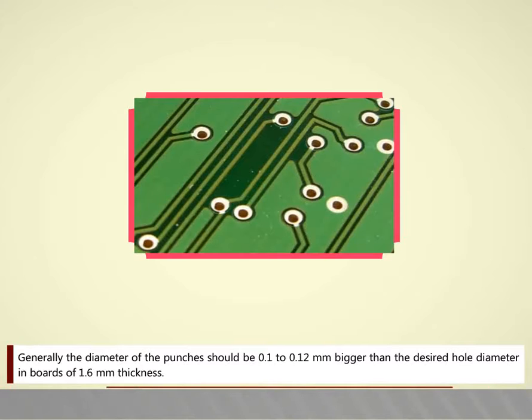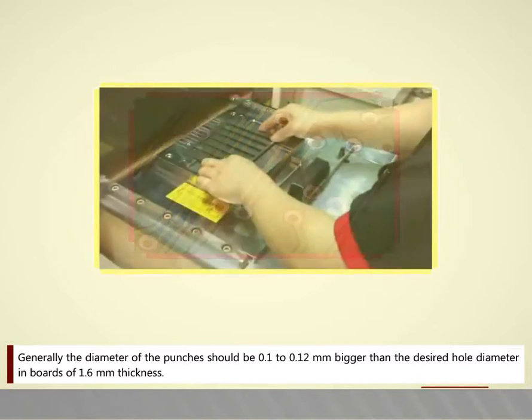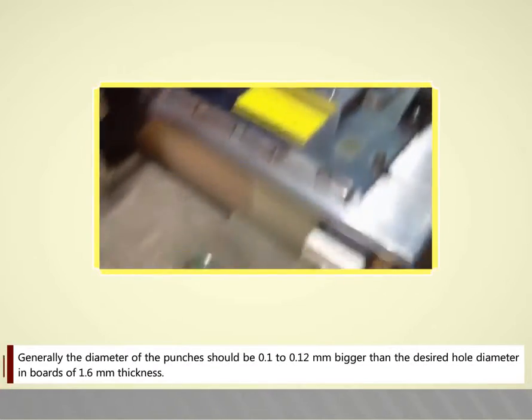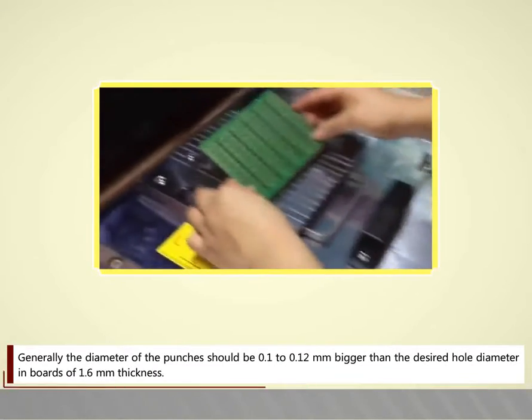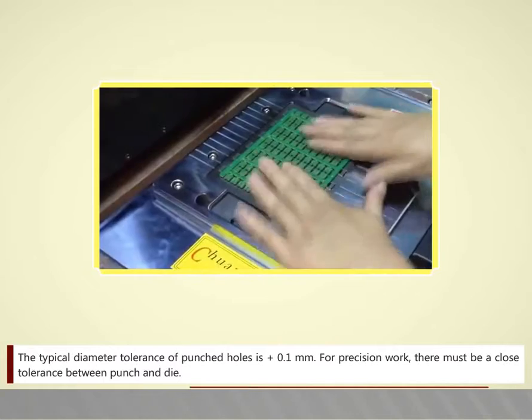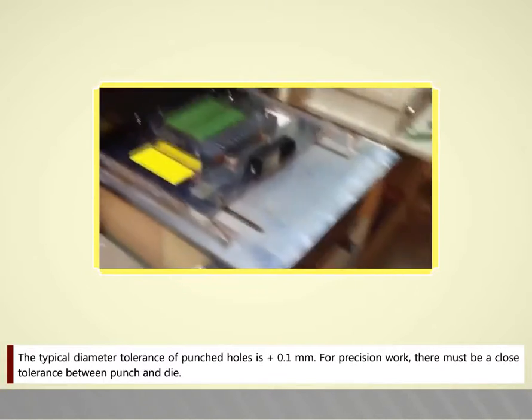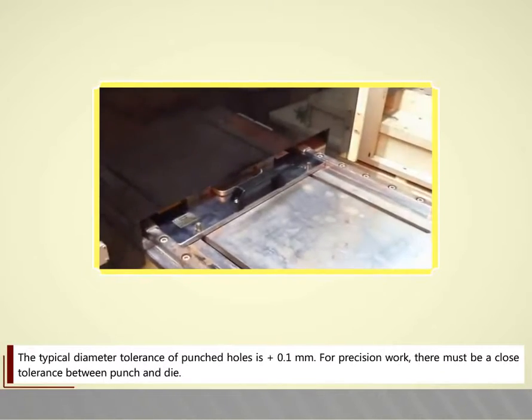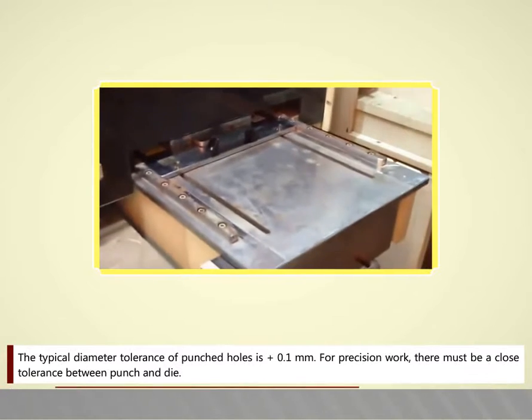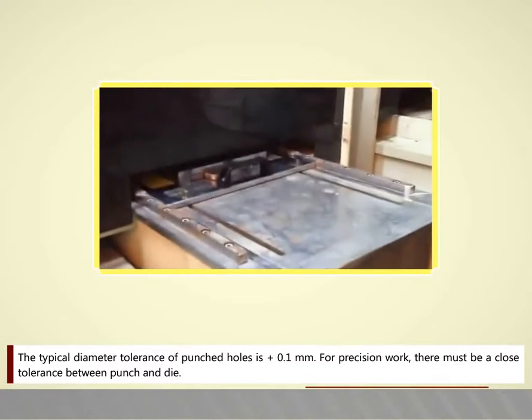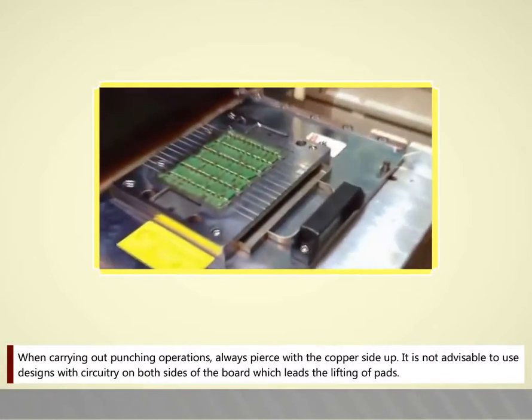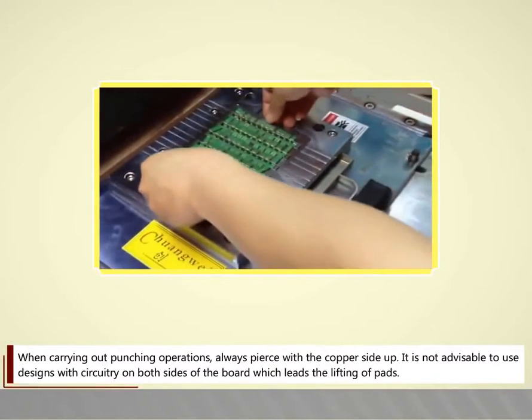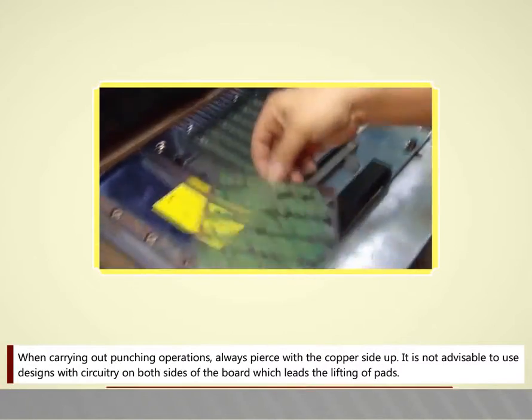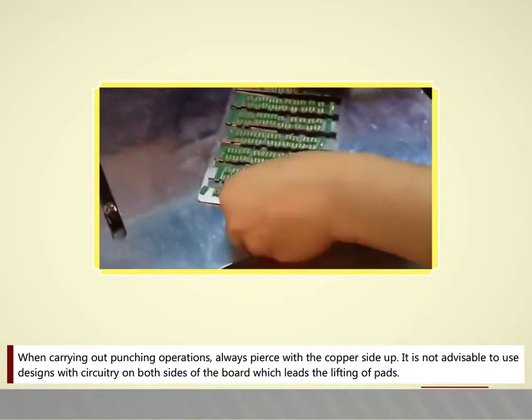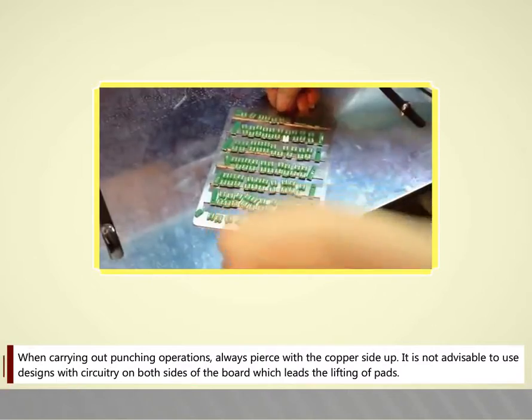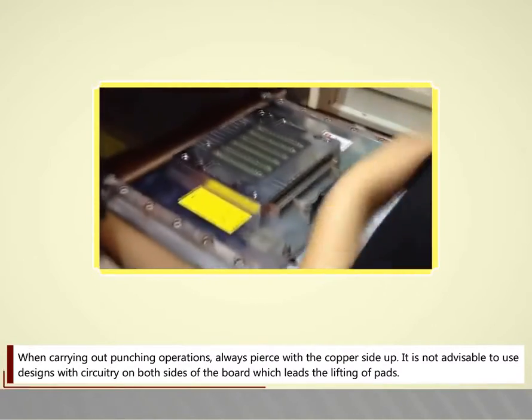Generally, the diameter of the punches should be 0.1 to 0.12 mm bigger than the desired hole diameter in boards of 1.6 mm thickness. The typical diameter tolerance of punched holes is plus 0.1 mm. For precision work, there must be a close tolerance between punch and die. When carrying out punching operations, always pierce with the copper side up. It is not advisable to use designs with circuitry on both sides of the board, which leads to the lifting of pads.